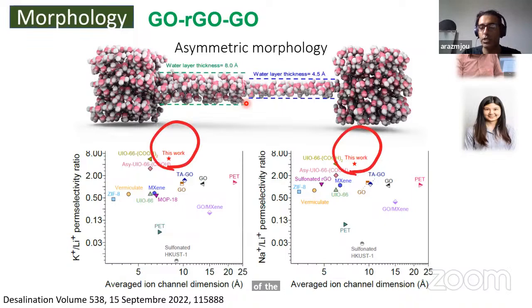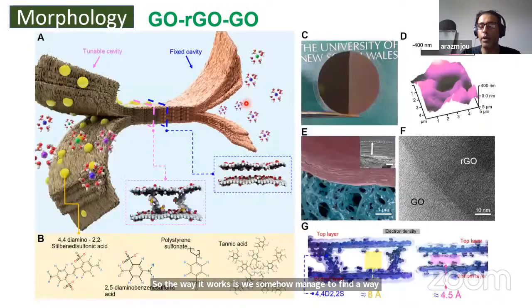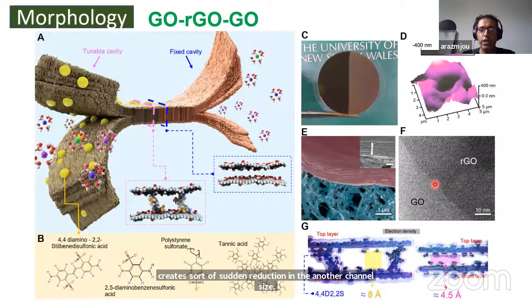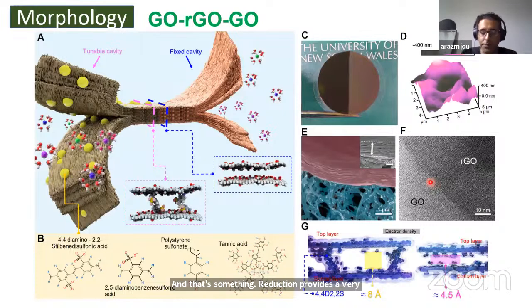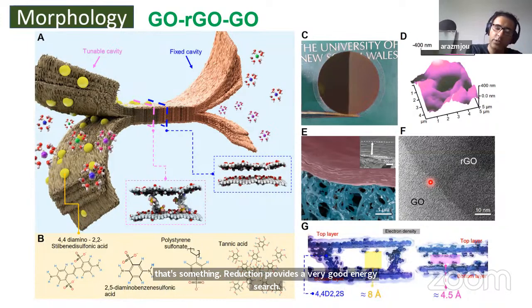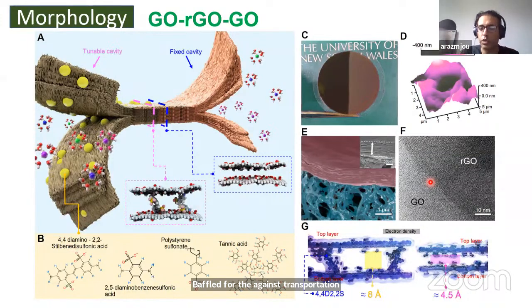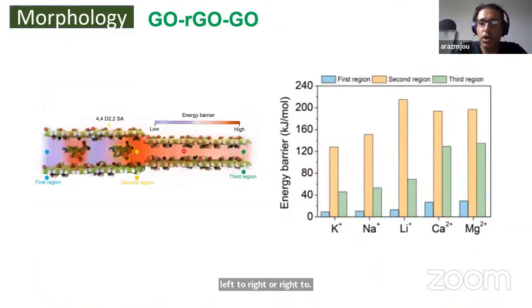The way it works is we found a way to create a boundary layer. As you move from graphene oxide to reduced graphene oxide, that creates a sudden reduction in the nanochannel size, and that sudden reduction provides a very good energy barrier against the transportation of ions from left to right or right to left. And you can see here, this is the region that has a high energy barrier.